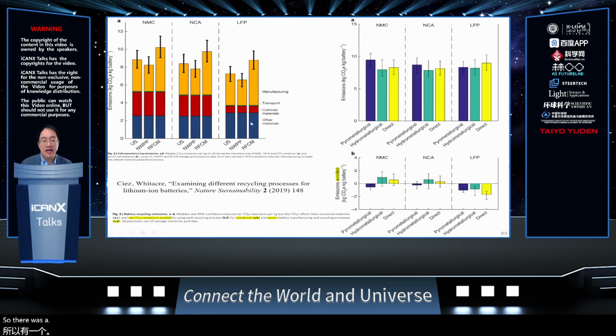So there was a recent study that compares the amount of CO2 for producing new nickel manganese cobalt batteries, new nickel cobalt aluminum battery. So this is a Tesla battery. And this is a new lithium iron phosphate battery compared to recycling with pyrometallurgical, hydrometallurgical, or direct recycling. So it turns out that for lithium iron phosphate, you actually emit more carbon dioxide compared to manufacturing new batteries. And so this is really kind of bad for the recycling business.